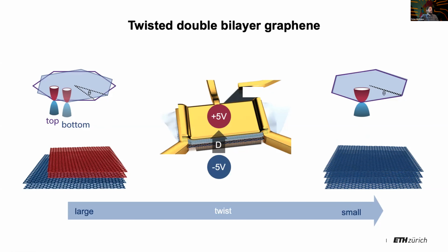But this is something we don't expect, but which is interesting on its own, because apparently if you just put two bilayer graphenes on top of each other, and you don't apply any voltage, then the thing is gapped for some reason. And this gap can be explained by the sort of asymmetry of the bulk to the surface, whereas the bulk consists of the two inner layers and the surface are the two outer layers.